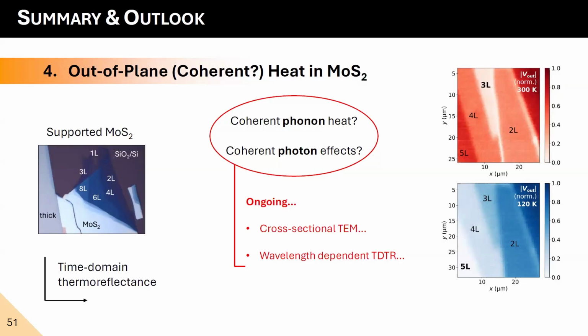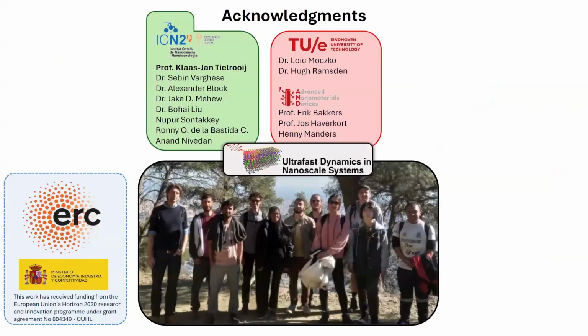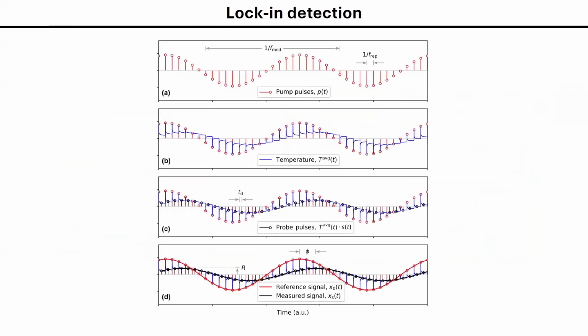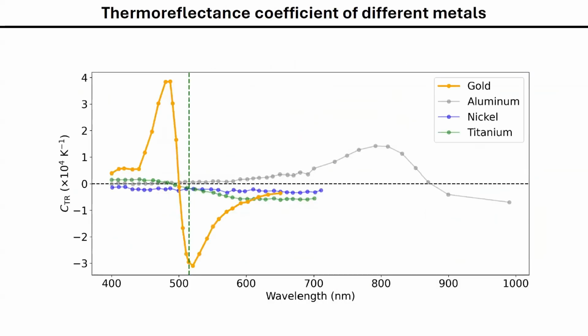Yes, basically we are currently performing probe wavelength dependent TDTR, and this relates back to the thermoreflectance coefficient of gold. Let's say we are probing here and the effect of 2D materials would produce maybe a shift on this resonance. It would be possible that this point with 0 thermoreflectance coefficient comes at our probe wavelength. So we are trying to perform measurements at different wavelengths here, and the idea is to see what changes, or if we can find the same results, or if it's all just consistent and heat can propagate coherently.